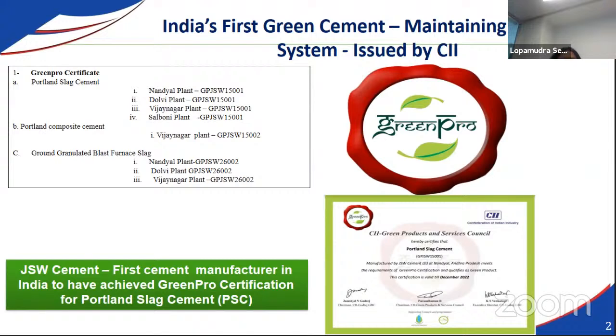Portland Composite Cement is also GreenPro certified, and so is ground granulated blast furnace slag, which is nothing but slag ground fine, to the tune of 4,000 square centimeters per gram, and mixed separately with clinker or OPC cement. Ready-mix concrete manufacturers are using it big time at construction sites. All of these products are IGBC GreenPro certified.